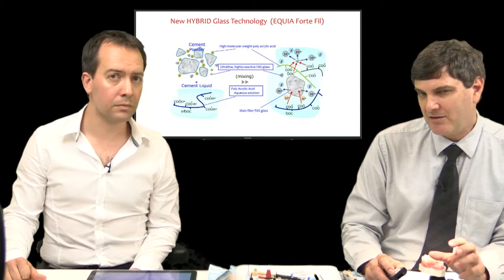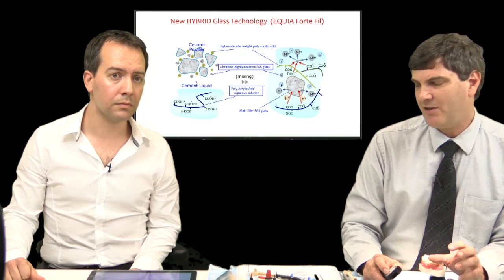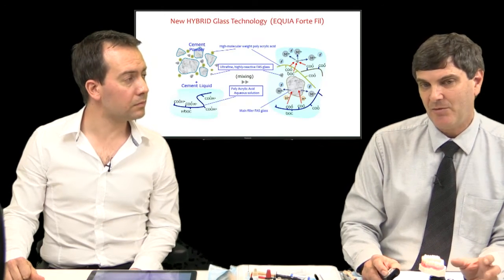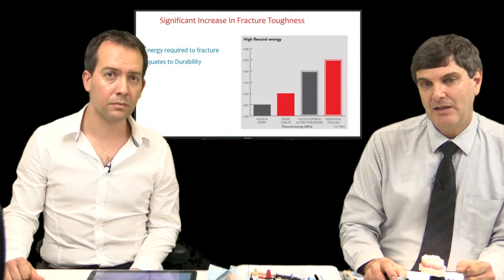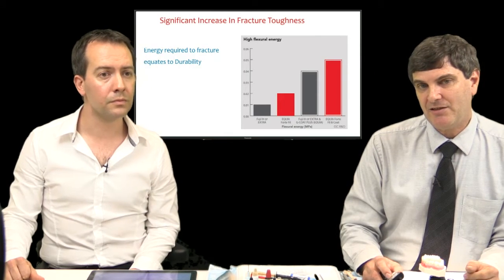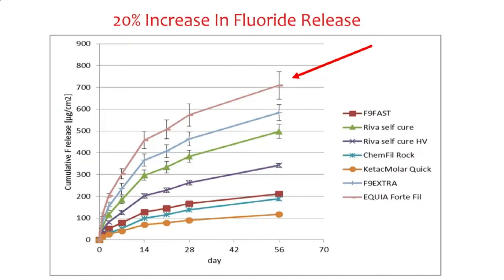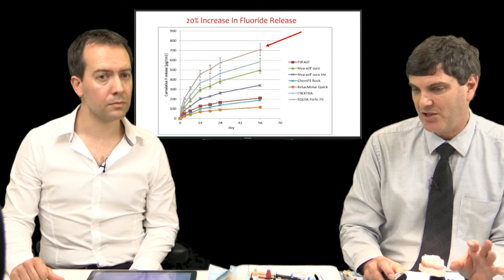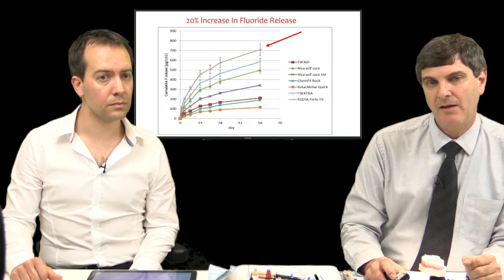In my hands and when I use it clinically, it doesn't appear to have quite the same aesthetics as the Fuji 9 Extra, but certainly a very nice product. And the data would tell us that there's a significant increase in fracture toughness with the EQUIA Forte Fil, and also an increase in fluoride by 20% over the Fuji 9 Extra. Still not quite as high as the Fuji 7 we mentioned before, but you know, these are good things, and this is why the manufacturers are continuing to work to give us better products.